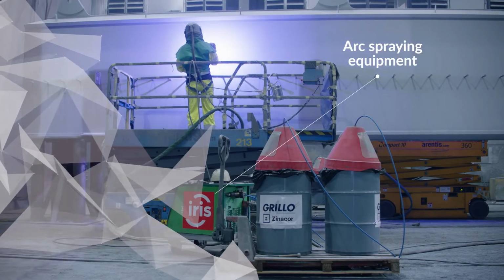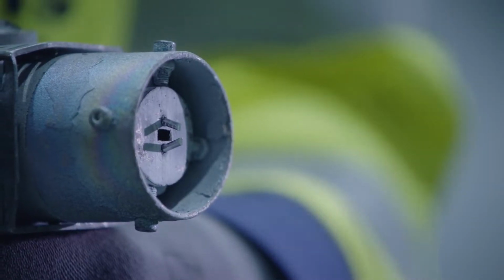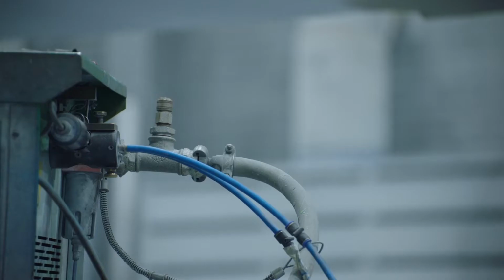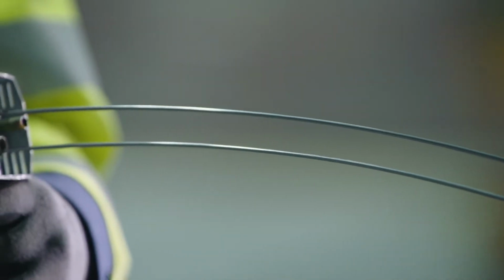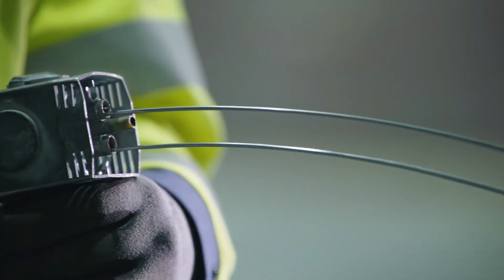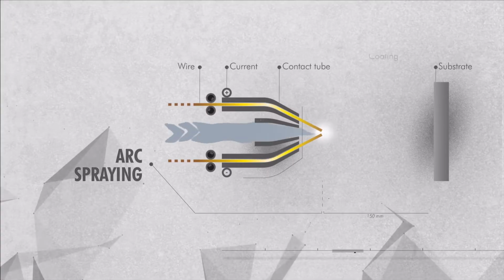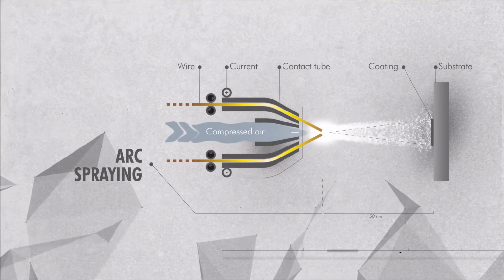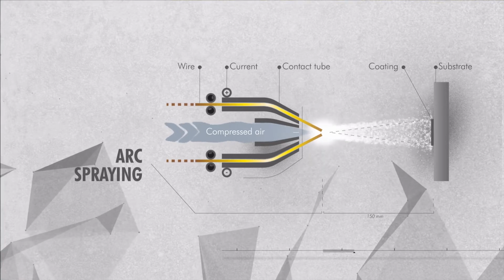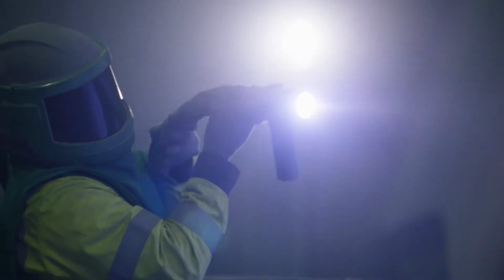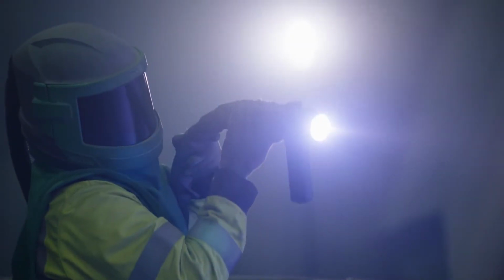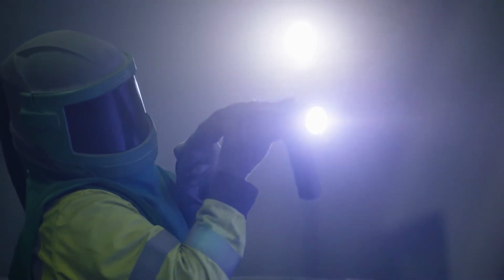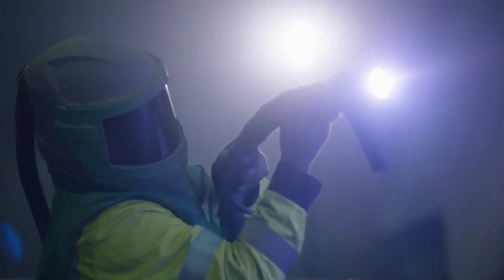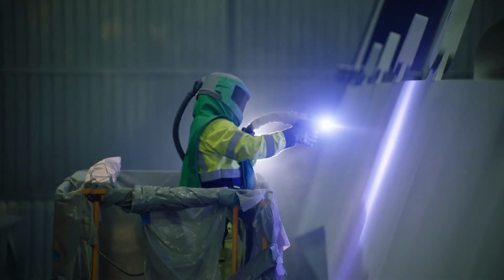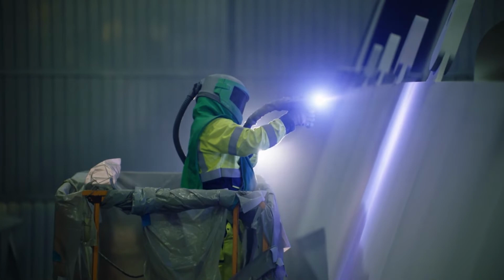Arc spraying equipment consists of the spray gun, power supply, and a pressure unit for dry air. Two electrically charged zinc or zinc aluminum wires are brought together at a controlled rate to form and sustain a stable electric arc. The heat generated by the electric arc melts the wire tips. The gun's atomizing airstream propels the molten material toward the substrate to form a metallic coating.